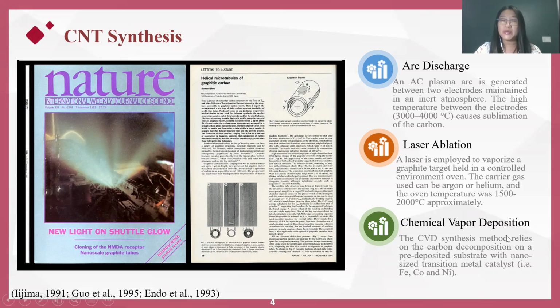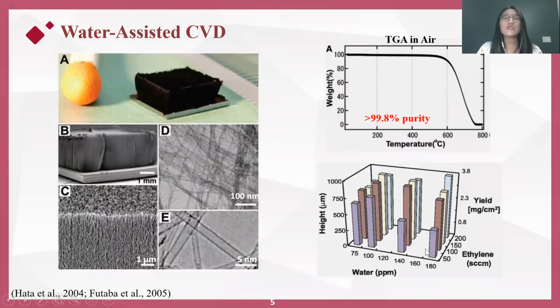The conventional CVD process, on the other hand, requires a remarkably lower temperature for the CNT to grow on a pre-deposited substrate. And this rationalizes its wide application, especially on the laboratory scale. In the early 2000s, a Japanese group took an innovative approach to introduce a controlled amount of water vapor into the substrate-based CVD process. And they yielded single wall CNTs, as shown in the SEM images here, with over 99.8% purity.